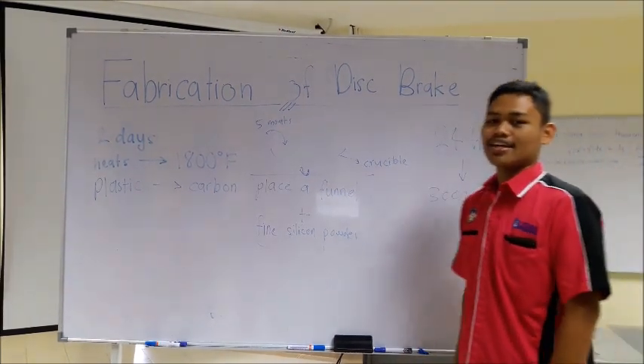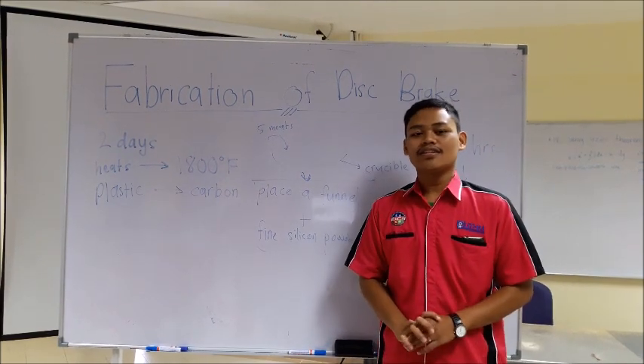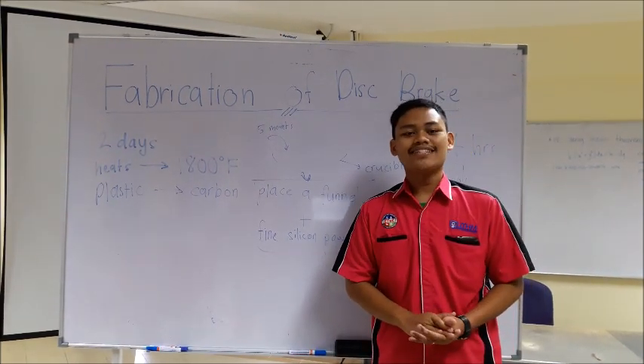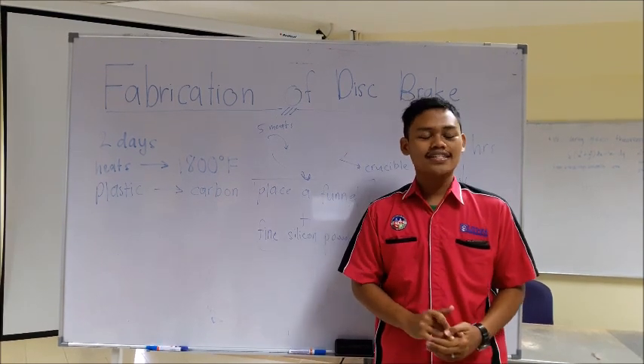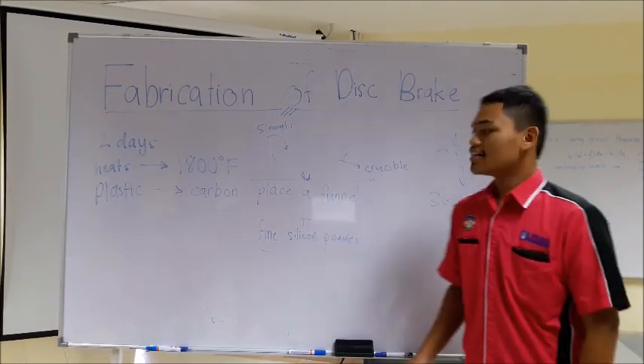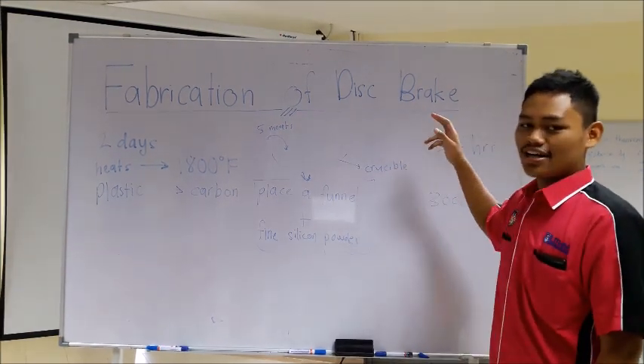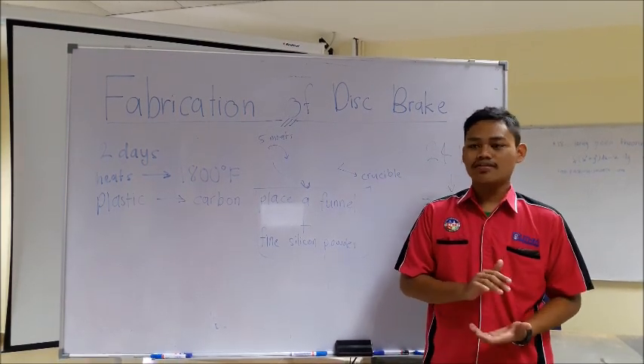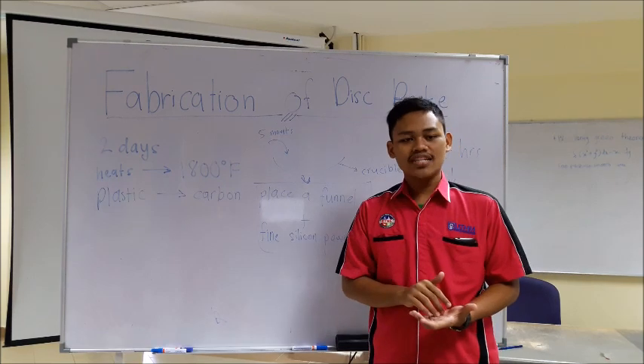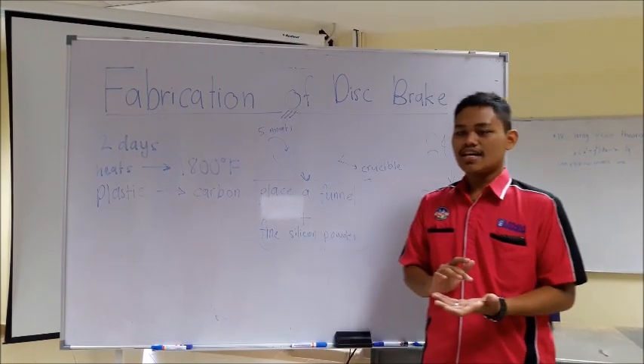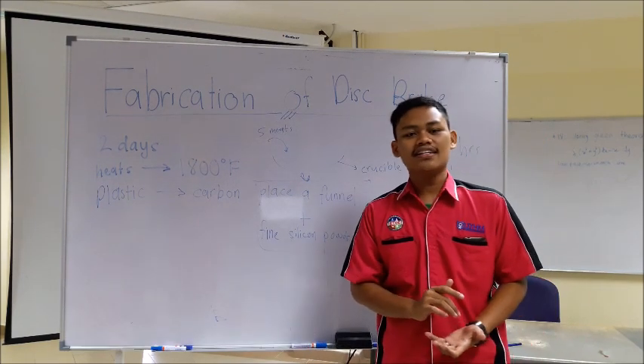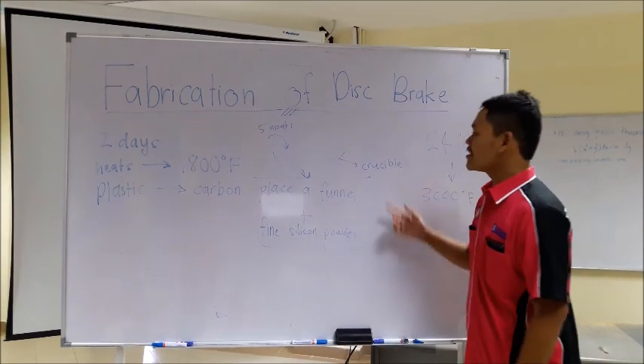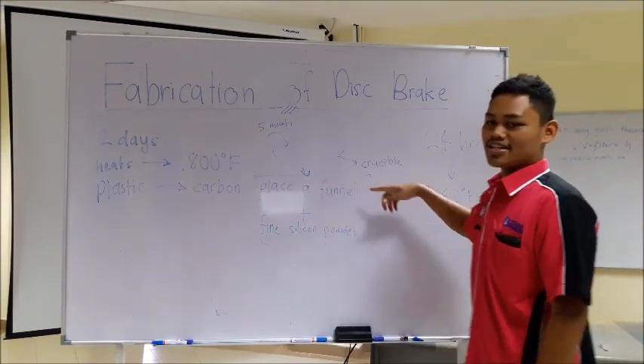Okay, once it is removed from the furnace, a drill machine bores the mounting holes on the disc ring, and then the disc ring goes to a chamber to receive a protective paint. This paint is used to shield the carbon disc ring from oxygen. This process is very critical, since at high temperature oxygen burns carbon. Hence, this anti-oxidation process increases the lifetime of the disc ring.